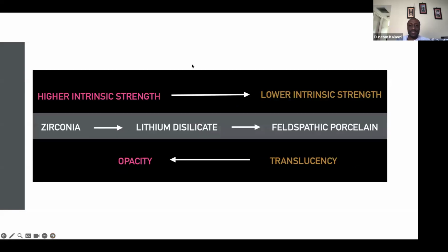In that regard, if you're designing restorations or choosing restorations, you should use zirconia at the back, perhaps lithium disilicate in the middle, and then feldspathic porcelain at the front. But you're trading one thing for another. As your strength increases towards the back, the translucence decreases, or the opacity increases. And towards the front, as your translucence increases, your intrinsic strength drops. So you need to be mindful of that.